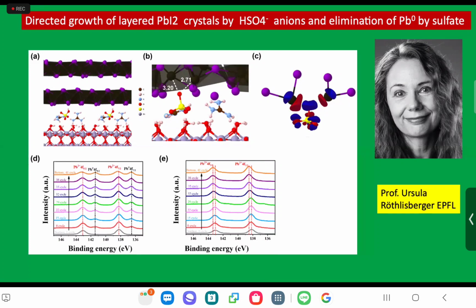The sulfate is guanidinium sulfate. The sulfate interacts with the tin oxide OH groups and forms an HSO4 minus anion on the surface that produces a dipole, and that dipole directs the growth. And the sulfate also interacts with lead and passivates lead, and so you get that better performance. Two actions. I hope that you will soon see that paper published.